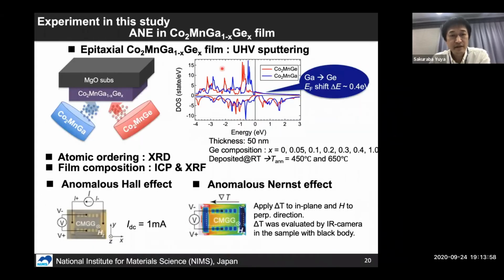So in our recent study, we fabricated the cobalt manganese gallium germanium thin film using the co-deposition technique with cobalt manganese gallium and cobalt manganese germanium targets. As you can see in this theoretical calculation of density of states for pure CMG germanium and CMG gallium, these two materials have nearly identical density of states near the Fermi level, but the Fermi level position is shifted by the change of total valence electron number. So from this calculation, we can expect that the Fermi level position can be tuned by changing the composition ratio of gallium and germanium.